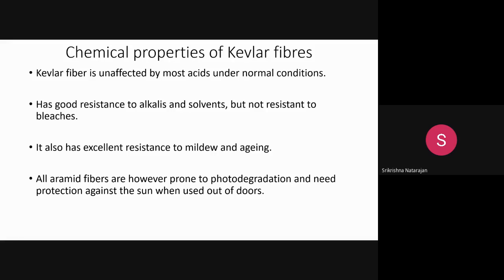But there is some problem associated with this Kevlar fiber. If you expose the Kevlar fiber to sunlight for a long time, it will lead to photo degradation. So these fibers have this problem. The UV resistance of Kevlar fibers is poor when compared with other fibers, so you have to add some UV protection agents during manufacture.